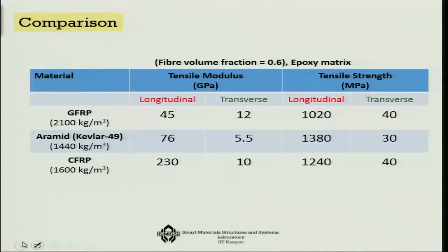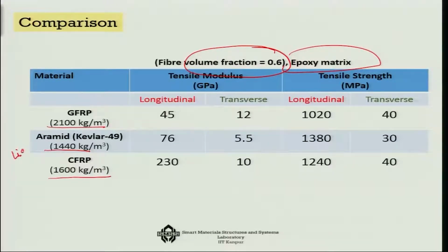Now if we compare the three types of composites with the same volume fraction 0.6 and the same epoxy matrix, otherwise it will not be a fair comparison. GFRP density is the highest, 2100. Polyaramides are the lightest at 1440, and CFRP is 1600. So you can call polyaramide the lightest and GFRP the heaviest among them.